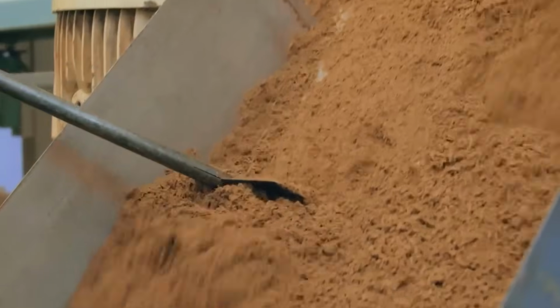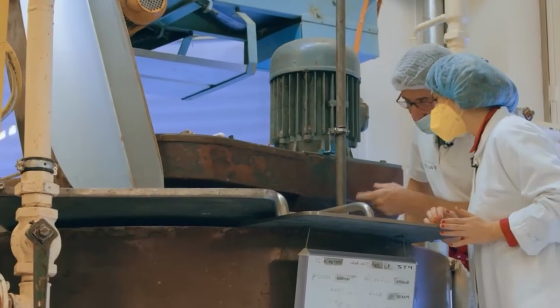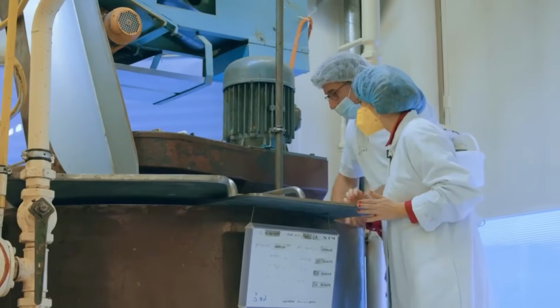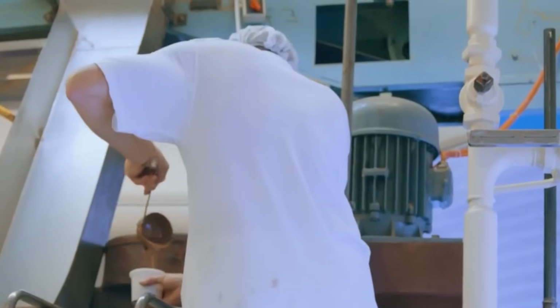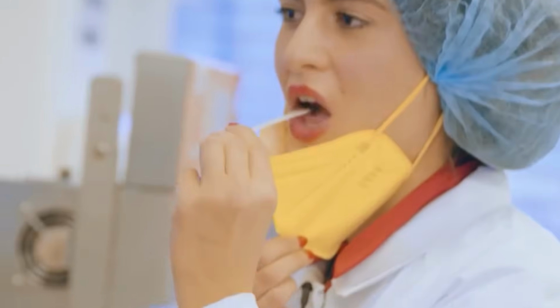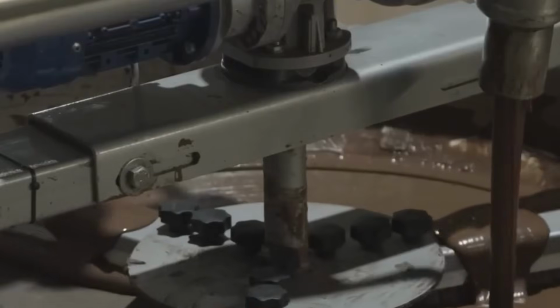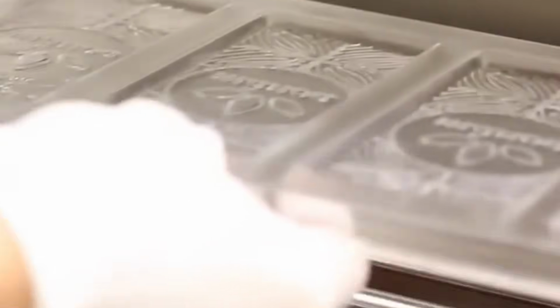Conching is done in elongated mixers called conches that slowly knead the chocolate at elevated temperatures, typically between 45 and 80 degrees Celsius, for several hours or even days, depending on the recipe. The purpose of conching is to develop flavor and texture. During this phase, volatile acids and off flavors are driven off by heat and agitation, while the friction created by the mixing reduces viscosity and smooths the fat dispersion.